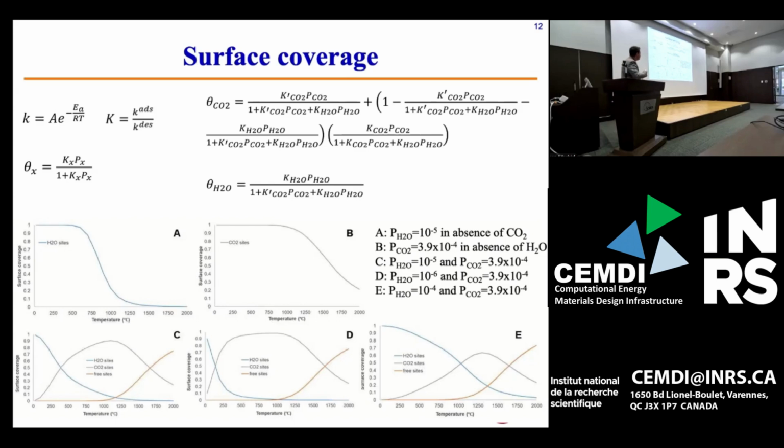And if we have humid conditions, our model showed that even at elevated temperatures, we'll have surfaces mainly of oxide and hydroxide. Carbonate formation will be delayed, and most of the surface will be catalytically active for the oxygen reduction reaction. Hence, understanding the gas mixture interaction with those materials is quite important, not only the catalytic activity for the target molecules we would have there.